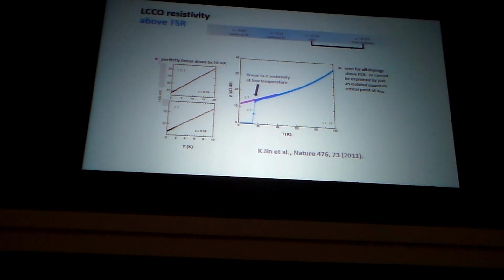What I want to talk about that is new and important is that when you go from this doping, where this Fermi surface reconstruction occurs, into the more metallic region, all the way to the end of the superconductivity, so over a range of doping, you find this linear in T resistivity at low temperature, you find linear in H magnetoresistance, and you find a logarithmic thermopower. So all three of those properties are totally different than the standard Fermi liquid here. Okay? So whatever is happening here in the normal state is very unconventional and unexplained, actually.